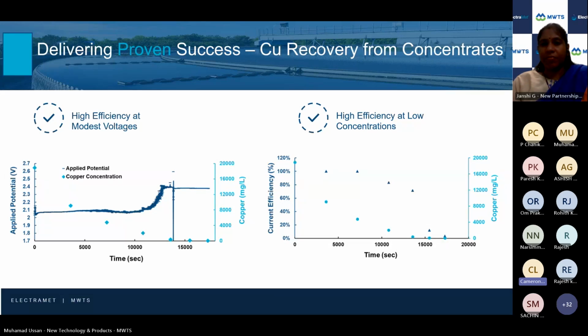In order to overcome this mass transfer, as you get more and more dilute, it takes more and more voltage, more energy to do that. And then looking down here on the right, you can see the current efficiency. So this is how much of the energy you're using is going to move the copper versus other unwanted parasitic reactions. So as we get down, again, on the darker blue triangles, you see it is very highly efficient and it slowly tails off. And once you hit around 1,000, 2,000 ppm, you see a huge drop off in efficiency.